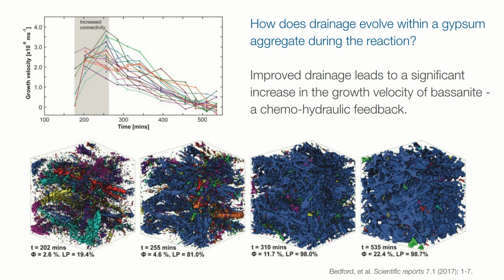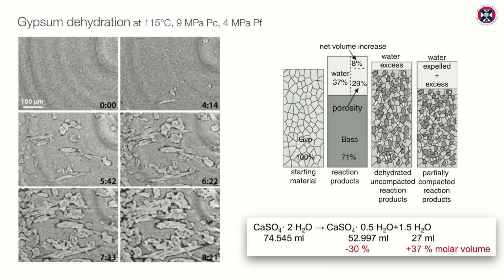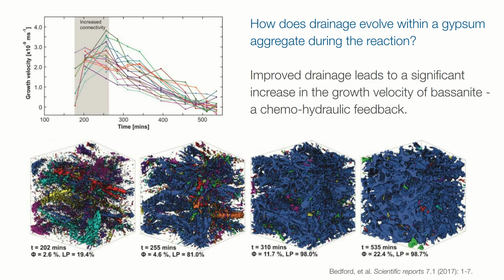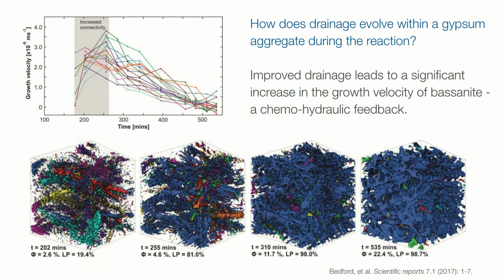What sort of images or what sort of data can we acquire from such experiments? What sort of insights can we gain? Just as an example here from a paper that we published a few years ago, where we essentially followed that reaction. Of course, now we can quantify the growth of these grains on the grain scale, while at the same time keeping an eye on what the porosity does and how the porosity evolves. And you can see here that as porosity interconnects between 202 and 255 minutes here, we see that the largest interconnected pore makes up 81% of the total porosity, and everything that is blue now is interconnected.